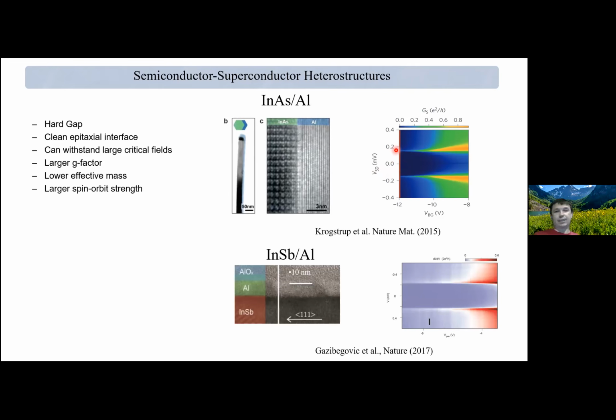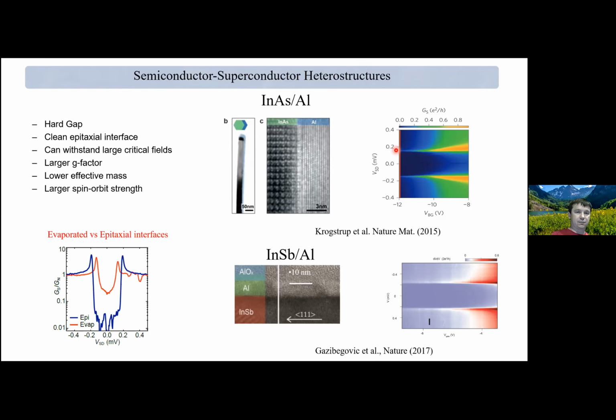Later on, a similar improvement was done for the indium antimonide and aluminum system. And indeed, if you look at the comparison between epitaxial growth of these interfaces and evaporated ones, we see clearly that epitaxial is much better than the evaporated method of depositing superconductor. So this was the key material science improvement needed for the field to actually improve the signal, improve the signature.